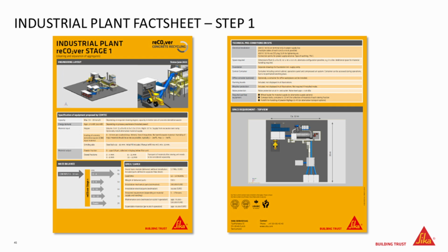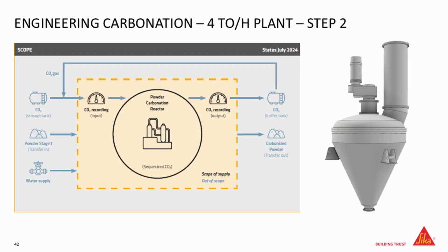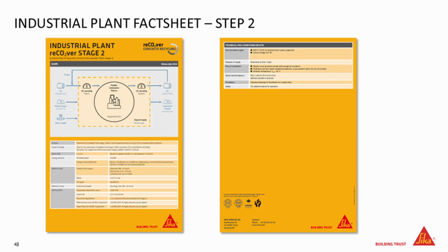Because at the end of the day, all this stays a nice story until there is a business case for somebody to invest in that. That's very clear. So we have it for this 20-ton plant. Step 1 is only the separation, and we also have it for step 2, because we developed a separate step 2. Basically we have a chamber where we put the powder inside and we put the CO2 inside and let it react, and then we can much more easily measure the uptake of the CO2 in several ways. And for that step we also have a fact sheet with all the things that you need, with CapEx and OpEx.